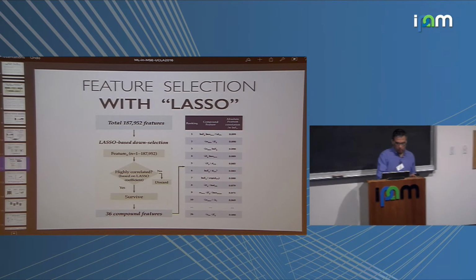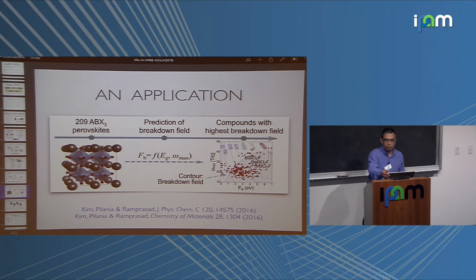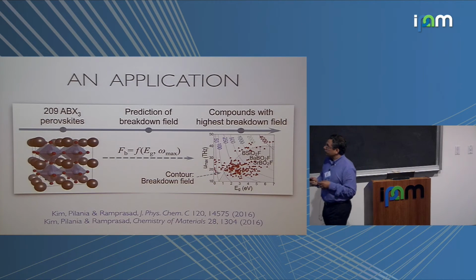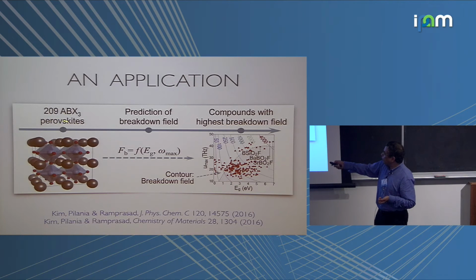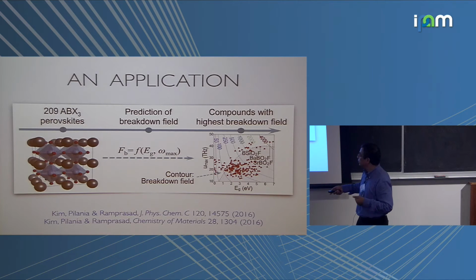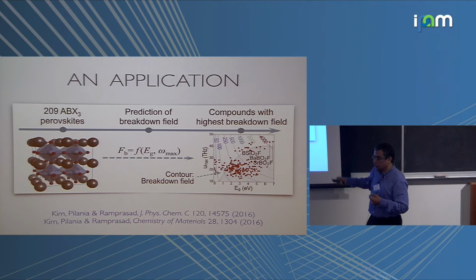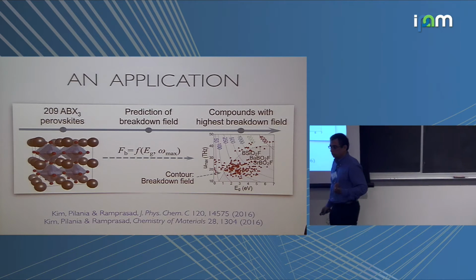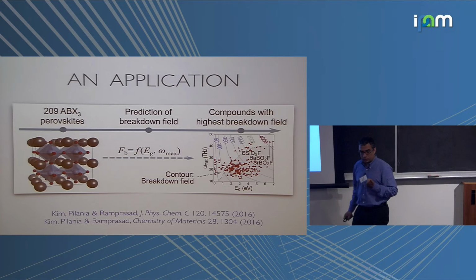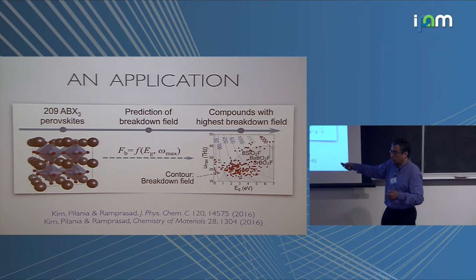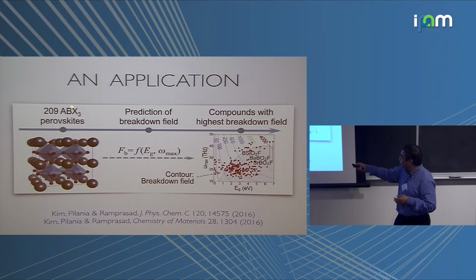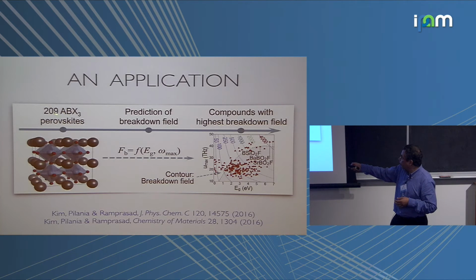Yeah. Okay, so let me show you this. We've gone further, right? So we now considered perovskites, ABX3 compounds, which occur in the perovskite crystal structure. We considered a couple of hundred of those, which are insulators, and which are stable in the perovskite structure. Not all ABX3 compounds are stable in the perovskite structure. Right? So we chose a couple of hundred of those, and for those, we computed the band gap and the phonon cutoff, used the formula I showed earlier, and here is a plot of the phonon cutoff versus band gap for those 209 cases.